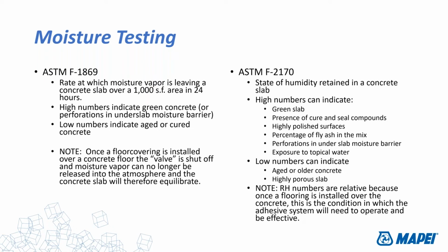So again, what the 2170 will tell you if you get high numbers on that, and we are focusing here on high moisture content, you get 99s or 90% and above, could indicate that you have a green slab. That means it's relatively young, 5 days, 7 days old, and the moisture content is a high number. Sometimes you can see the presence of cure and seal compounds on the top of that concrete. Concrete, when it's placed, typically gets some sort of a cure and seal material on the surface to retard the amount of moisture coming off of it. The reason they do that is to prevent or try to control that concrete slab from curling. So they lock the moisture in to try to stabilize the concrete slab.